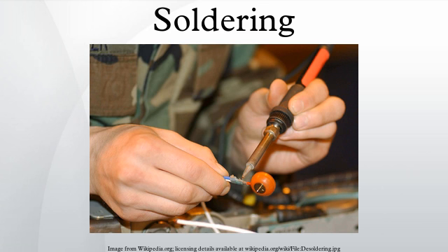Desoldering wicks contain plenty of flux that will lift the contamination from the copper trace and any device leads that are present. This will leave a bright, shiny, clean junction to be resoldered. The lower melting point of solder means it can be melted away from the base metal, leaving it mostly intact, though the outer layer will be tinned with solder. Flux will remain, which can easily be removed by abrasive or chemical processes. This tinned layer will allow solder to flow into a new joint, as well as making the new solder flow very quickly and easily.